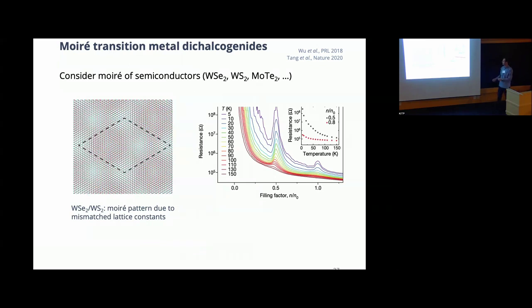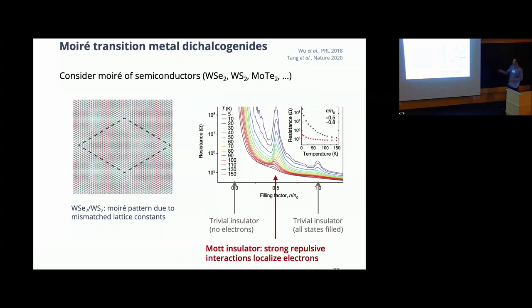Okay, what are we looking at here actually? So at zero filling, the system is empty. You don't have any electrons, so the resistance is obviously infinite. If the system is fully filled, you get a kind of trivial insulating state, a trivial peak in resistance. And now here the crucial insight is that also at half filling, so if you have exactly as many electrons as lattice sites, you get strongly peaked resistance here. And this is what we call a Mott insulator.